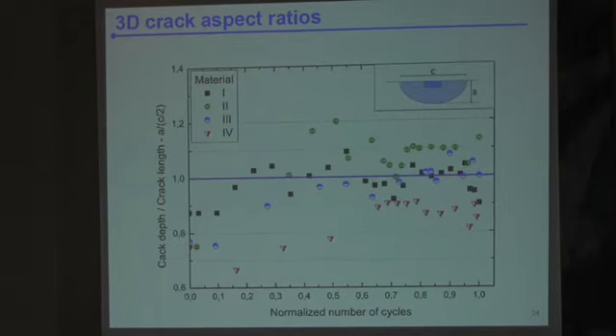This is for one sample for each material, the evolution of the crack depth over crack length ratio as a function of the number of fatigue cycles, but this is normalized by the number of cycles to fracture. So this is the end of life for all samples. So you see gradually it increases and it levels off at a value which is centered around 1 here, but one sample or one material is markedly different and it's below.